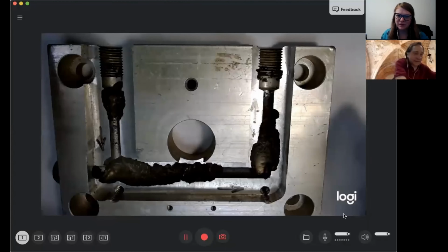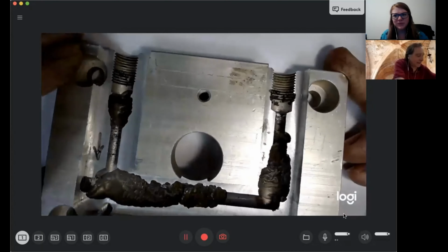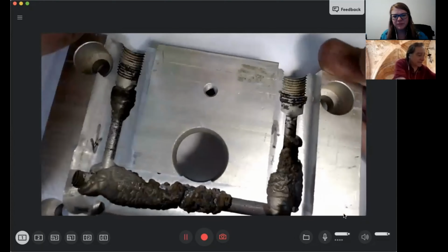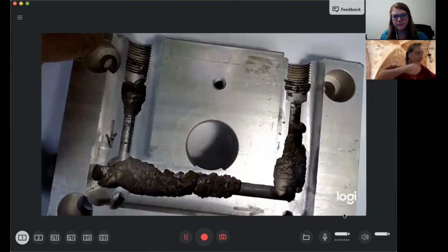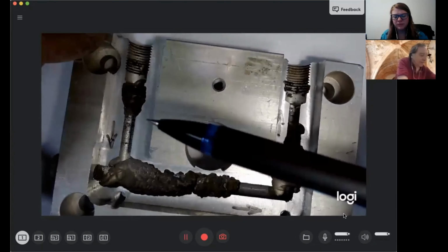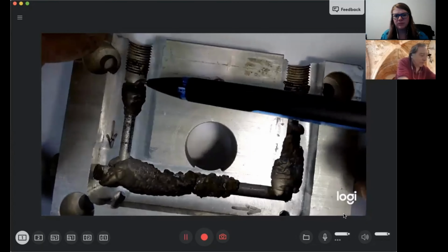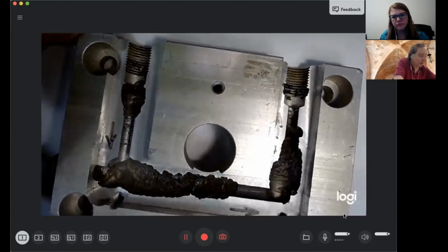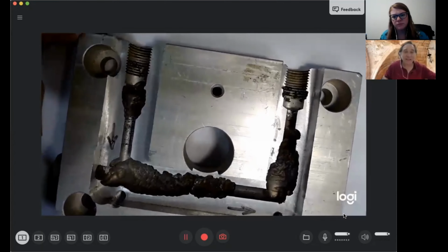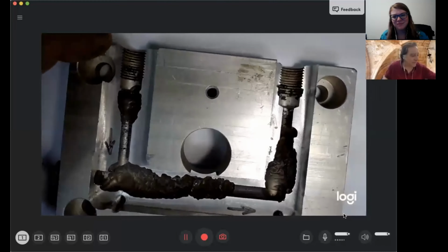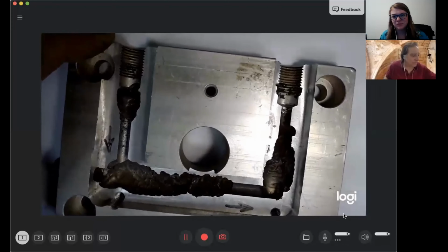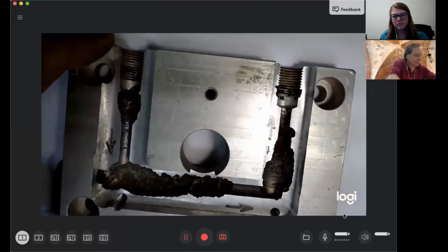So this is a funny thing. This is a heat sink for aluminum. A bunch of electronics attaches to this, and here is where the water flowed through. It's kind of funny that as soon as the water got turbulent, it dissolved away the aluminum, and then it got laminar again. Then it turned this corner and got turbulent. This is an example of erosion corrosion, which is kind of a funny problem to have. That's one aspect of corrosion. And the whole thing was that the pH of the water changed.